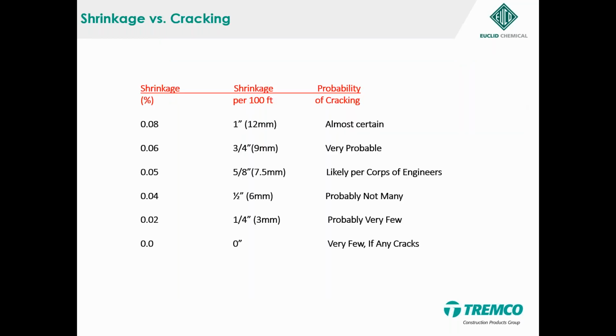Also, when you're working on shrinkage versus cracking on this particular part, all of these calculations are actually done by structural engineers. So when they're looking at shrinkage design in the reinforcement, it means that if they're designing at 0.08%, you're likely to have a 1 inch crack. If they're designing at 0.05, you're likely to have 7.5 mm, okay, for over 100 feet length. So these are some things which we should keep in mind when we are designing concrete, or planning our concrete, or when you are putting things together for high performance concrete.